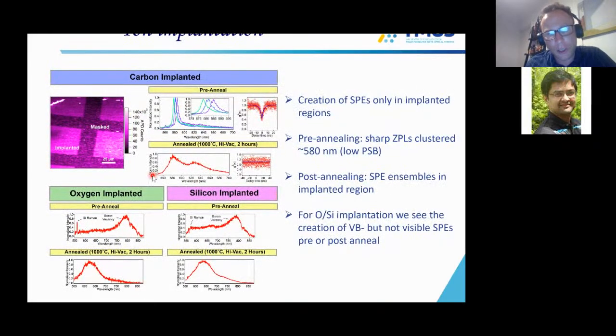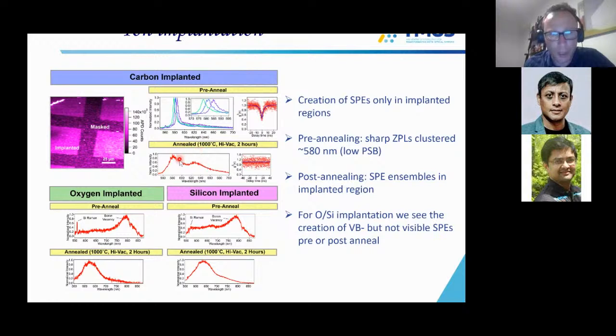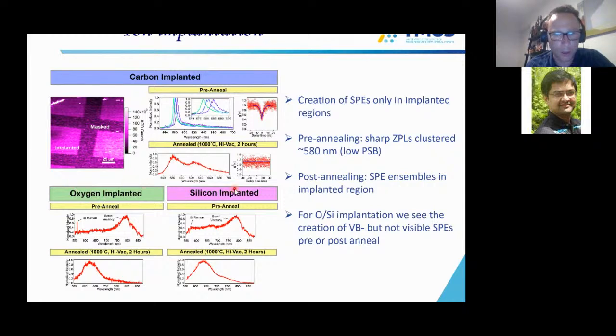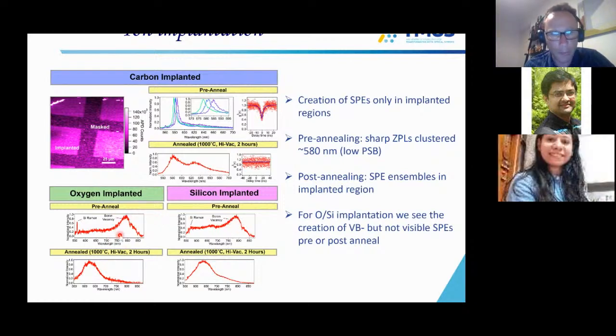You can do, of course, ion implantation. So this is an implanted carbon sample, which shows exactly the same lines. If you anneal the system, which means that you let the atoms in the crystal diffuse, you see again the same ensemble measurement. And if you do a control measurement of oxygen or silicon, you see very broad emission in the IR range, which has nothing to do with our single emitters. I will talk about this emission towards the end of my talk.